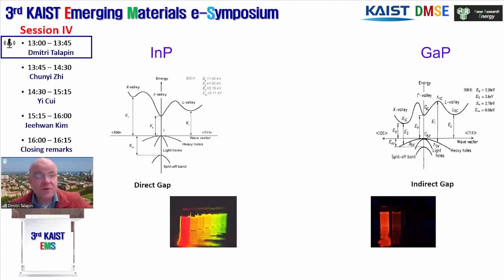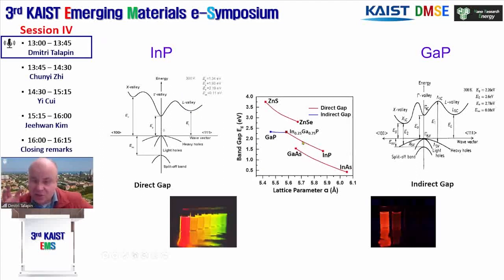Another very interesting point about indium gallium phosphide is that as we move through the composition, we go through a very interesting change in the band structure. Indium phosphide is a direct gap semiconductor, but gallium phosphide is an indirect gap semiconductor. As a result, we switch at some point from direct to indirect as we change the indium to gallium ratio. And that's exactly what we see experimentally. In the indium-rich case, up to about 65% indium, we have pretty bright emitting, well-behaving quantum dots where we can use the amount of indium or gallium introduced into the quantum dot to control the band gap. But as soon as we cross into the indirect gap, the photoluminescence disappears, and that allows us to make a very important fundamental conclusion